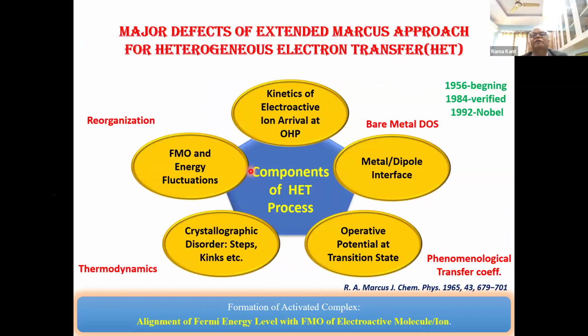Why do they have an issue? They have an issue because the major defects arise from the fact that there are two stages in electron transfer at a heterogeneous interface. First, your electroactive species has to reach the OHP. So the kinetics of electroactive species or electroactive ion arrival at the OHP is important. It will be seen that when electron transfer becomes very fast, only the ion arrival kinetics control it. That we will call barrierless electron transfer. But it will have some finite rate, not very limited, but finite.